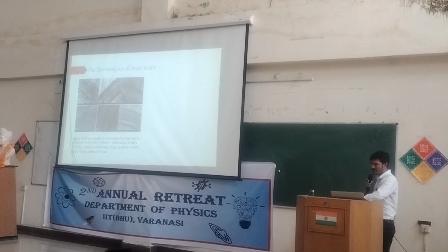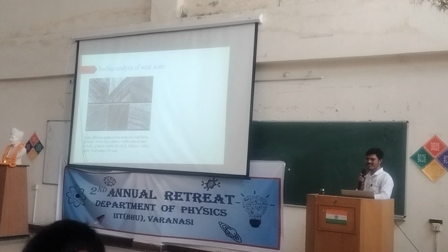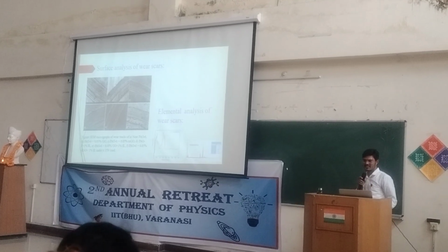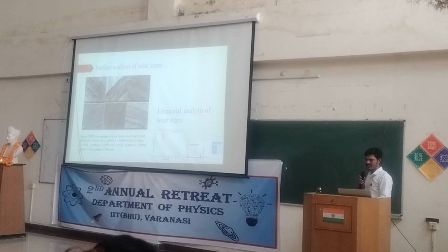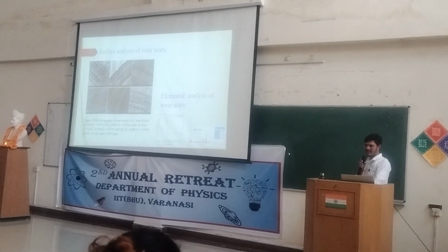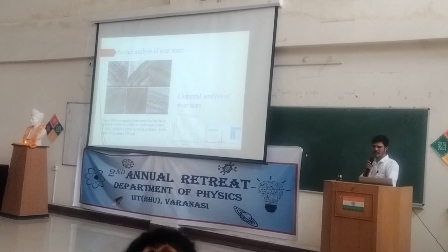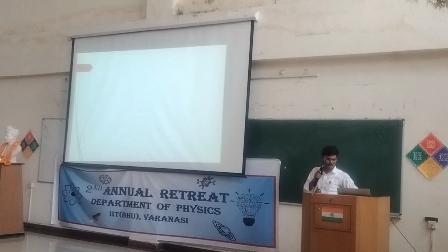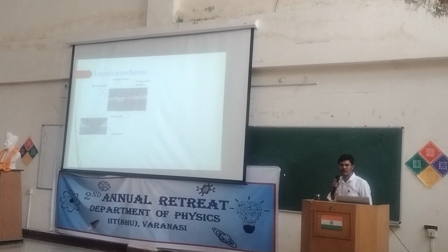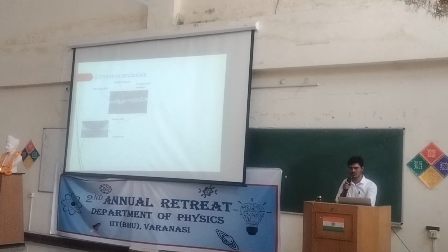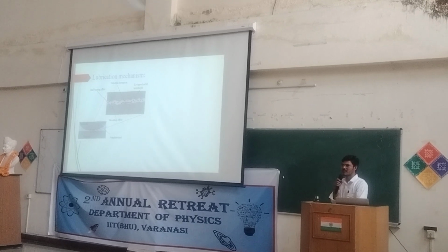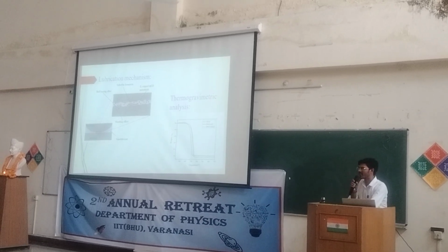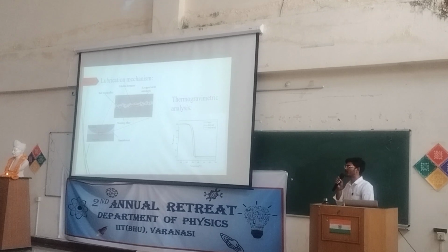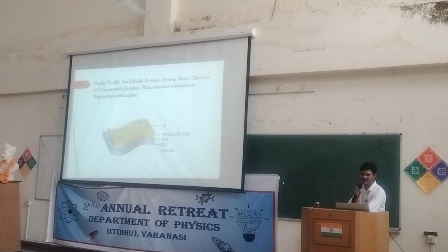And after that, we performed the surface analysis of wear scars, and elemental analysis of the wear scars by using SEM, EDX spectrum and Raman spectroscopy, and to elaborate the lubrication mechanism, we use elemental analysis of the wear scar, and also we have used thermogravimetric analysis to study the thermal stability of the lubricant.